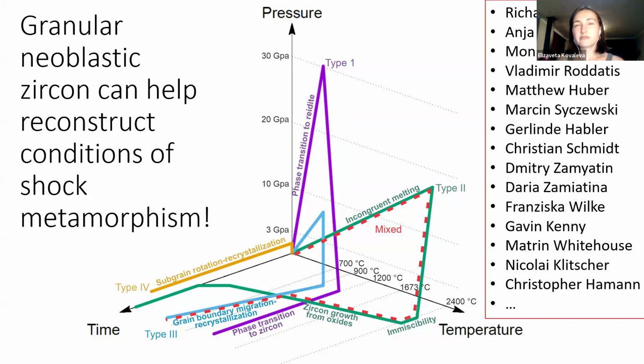And so very generally, you can assign those textures to geographical or stratigraphic levels in the crater, but they can be very much mixed together, to the point that you will see two crystals sitting next to each other in the same fragment. One will be completely intact and one will be shocked to dust. This shock metamorphism process is very inhomogeneous, and it just very much depends on the local environment.